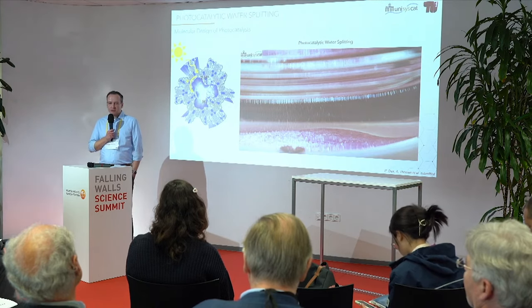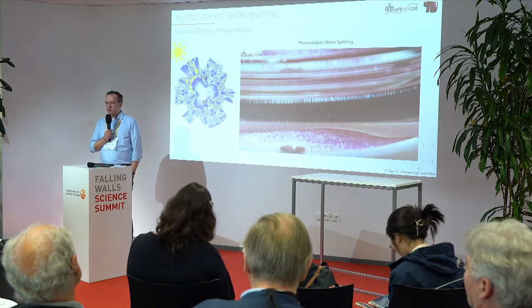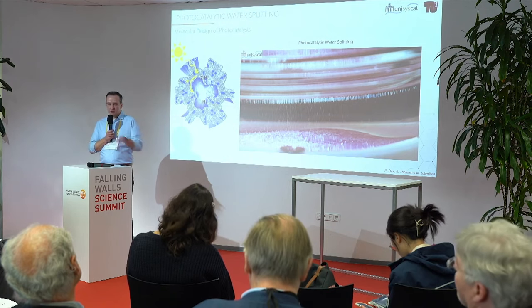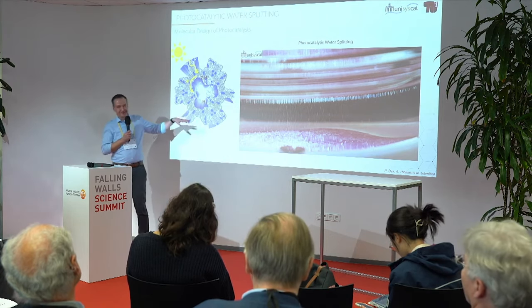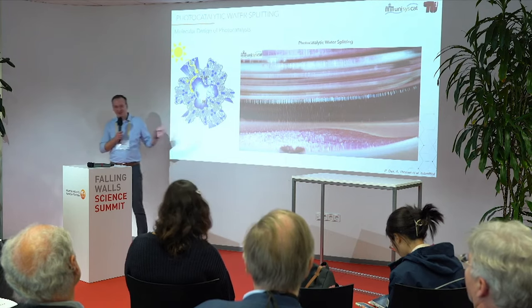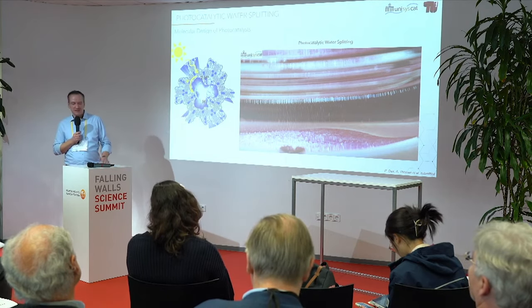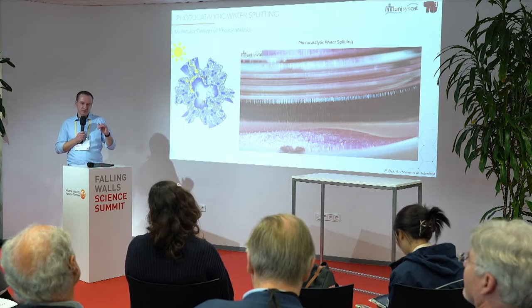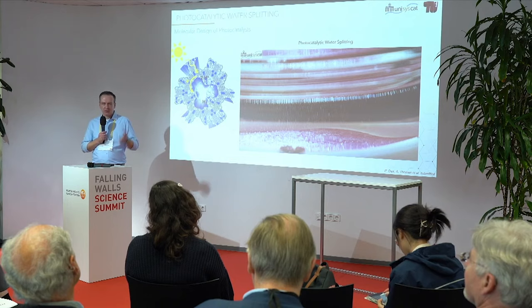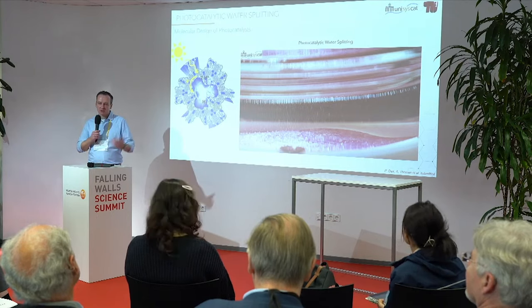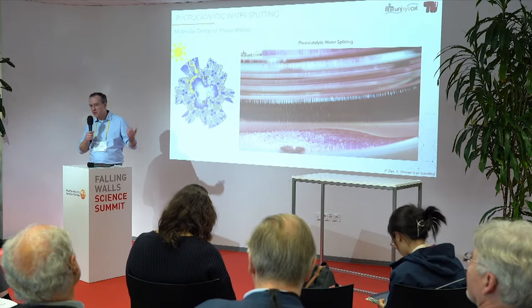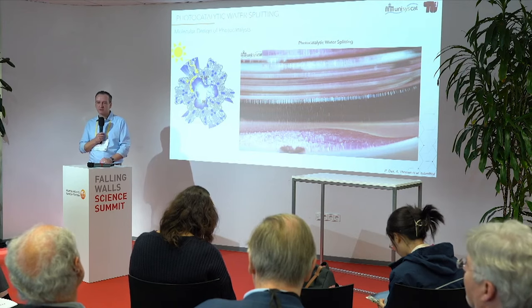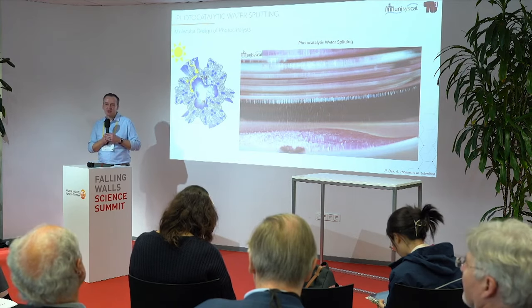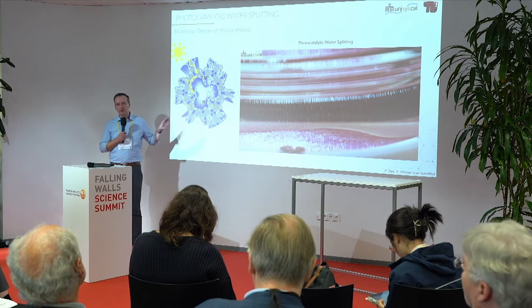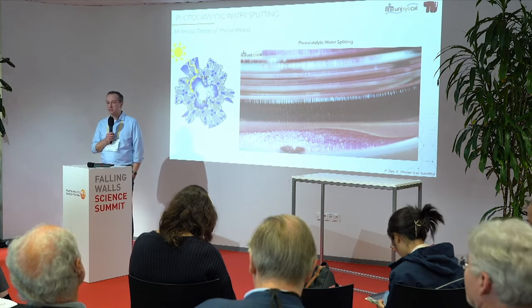I would have been very careful with these questions 2 years ago, but now we have developed systems which are super rock stable, really, which are fully aromatic. Actually, this one here, if you look very close, you can see that the structure is a bit different from the one I showed. It is a fully aromatic system with quinoline bonds, and you can put acids and bases on it, you can boil it in water. I think these are very promising systems. Of course, we just heard it is lab scale, so we can do it for 40 hours or something like this. Industry will say, great, 40 hours, we need 2 years or so. This we couldn't test so far, but at least from the chemistry, we are at a point that I can say these materials are really, really stable.